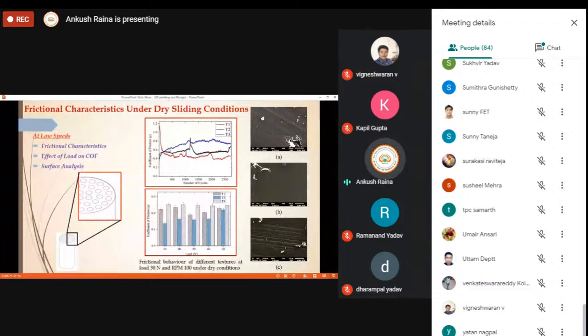But after some time, when the steady state condition is achieved, the coefficient of friction curve tends to stabilize. So after some cycles, there may be a formation of transfer film due to entrapment of the soft particles. Basically, PLA is a soft material, and the particles which are worn out from that surface can be entrapped, and that may help in the formation of a smooth film. If there is a smooth film between the sliding components, that will ultimately reduce the coefficient of friction and reduce the resistance caused by the sliding. So for texture 3, T3, which is again shown over here, this one.